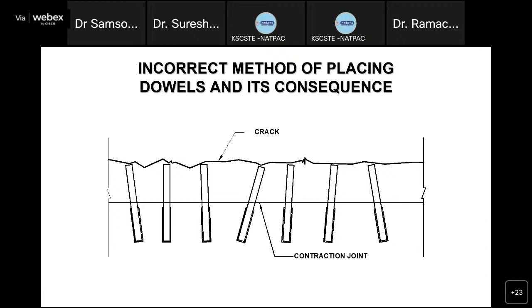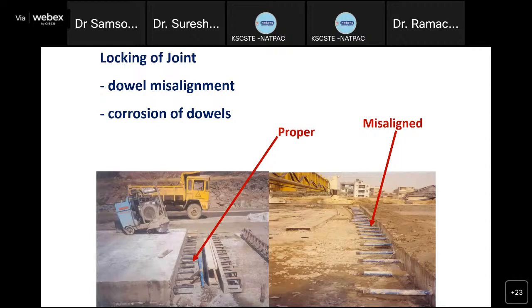properly placed dowel bars versus improperly placed dowel bars. Now here you are seeing in plan as well as in elevation, dowel bars placed properly. Now I would say improperly placed dowel bars, as you can see in the photograph, improperly placed, misaligned dowel bars are worse than not providing dowel bars. Or in other words, the best way of construction of roads is to provide dowel bars properly. If we cannot provide dowel bars properly, it is better not to provide dowel bars. Otherwise, it will create bigger damage than not having dowel bars. Now, if the concrete surface has fully deteriorated, we can go in for full depth repair.